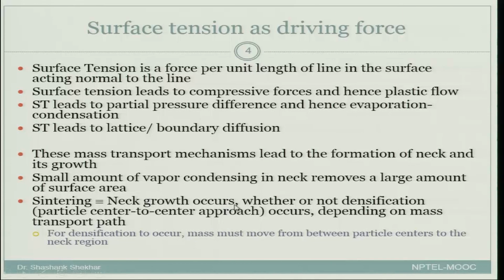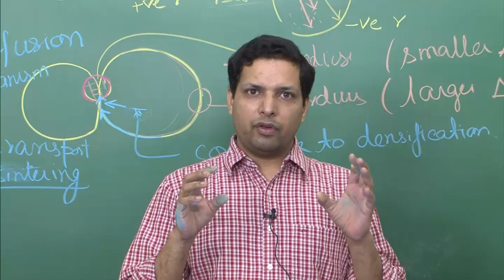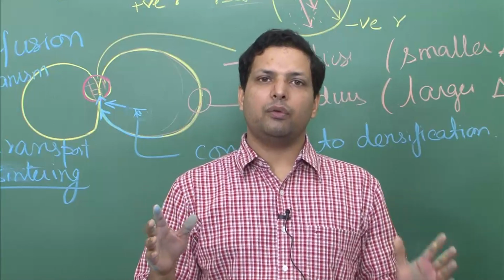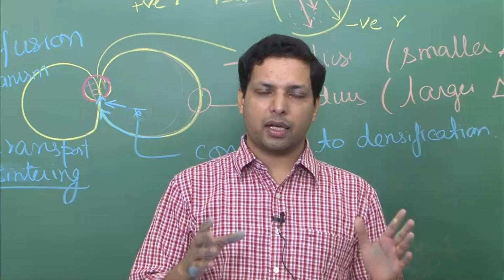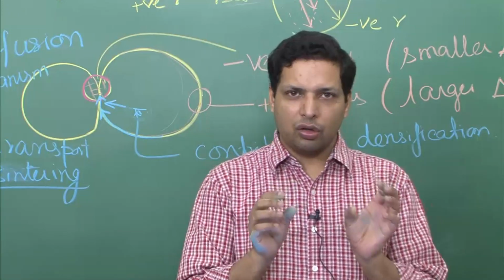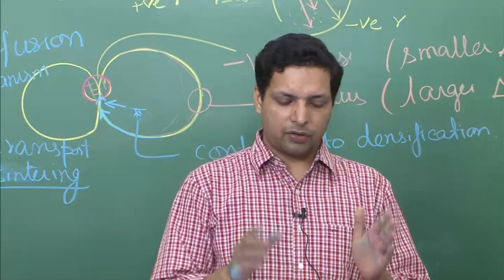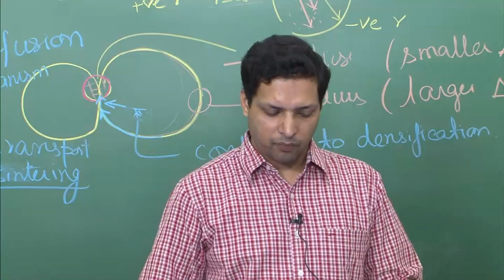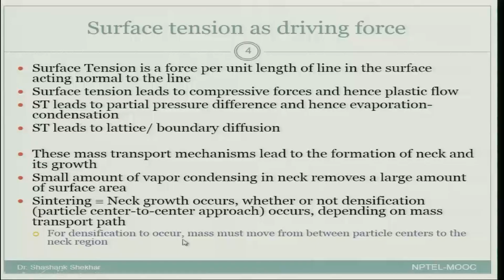Sintering is equal to neck growth. When the neck growth occurs, it is sintering, whether or not densification occurs. And what is densification? It is particle center to center approach. However, I am also saying that in the overall big picture, when we look at a much larger number of particles, sintering will always be accompanied by some amount of densification, even though if you look from the definition of center to center approach, there may not be densification. For densification to occur, mass must move from between particle centers to the neck region, which is what we saw when we had lattice diffusion taking place.